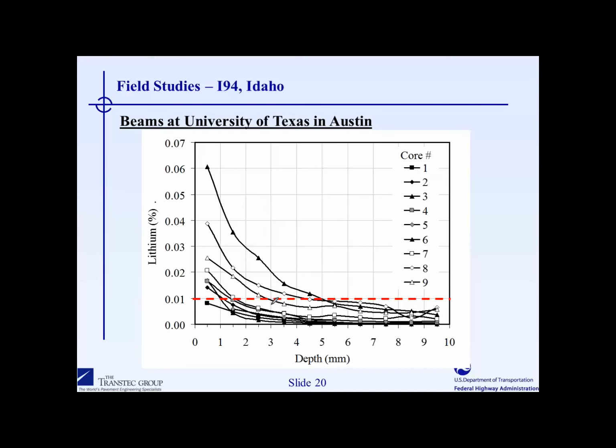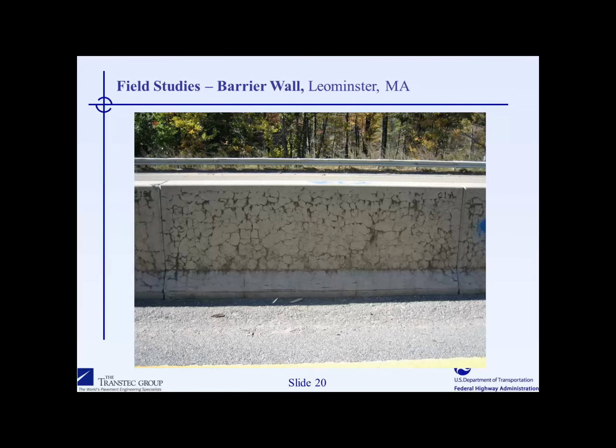And since we did this study about 8 or 9 years ago, our team has done quite a bit of follow-up work on it and have shown pretty definitively that topical treatments of lithium into mature field-type concrete results in a very similar lack of penetration.